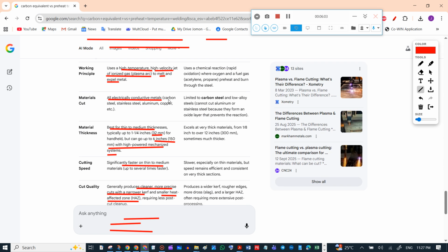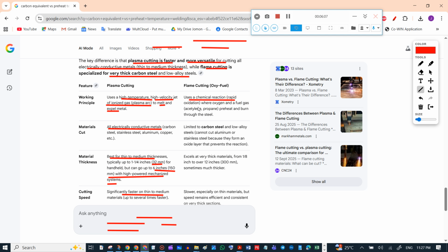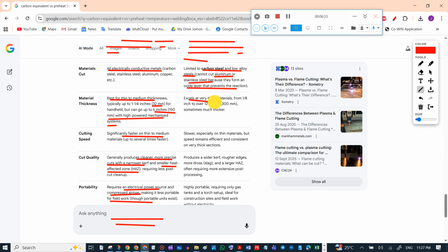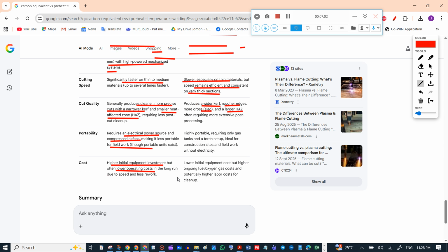Whereas flame cutting uses a chemical reaction, that is rapid oxidation, where oxygen and fuel gas like acetylene and propane preheat and burn through the steel. It is limited to carbon steel and low alloy steel because aluminum or stainless steel forms an oxide layer that prevents the reaction. It excels at very thick metal from 1/8 inch to 12 inches, that is 300 mm, sometimes much thicker. It is slower especially on thin materials, but speed remains efficient and consistent on very thick sections. It produces a wider kerf and rougher surfaces, more slag and a larger heat affected zone, requiring more extensive post cut cleanup.